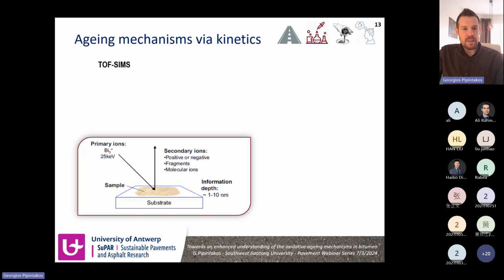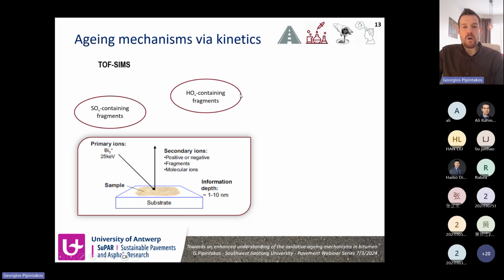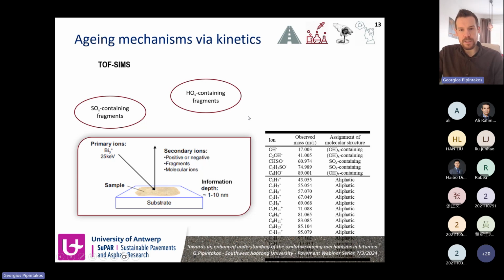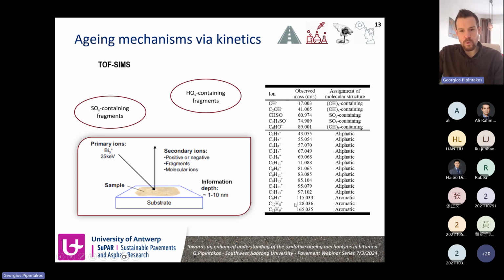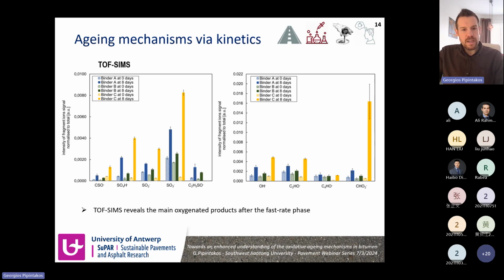So we then used another technique, the time of flight secondary ion mass spectrometry, or TOF-SIMS. The principle is based on the fact that the bitumen film is bombarded with bismuth ions, and the emitted ions give information about the fragments of bitumen. And we were able to classify all the fragments into sulfoxide containing and oxygen containing or hydroxide containing fragments. And these are all the molecular assignments that were observed for all the bitumens and were grouped later in these two big categories.